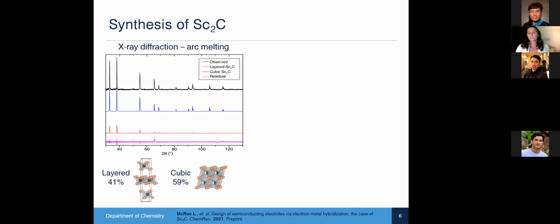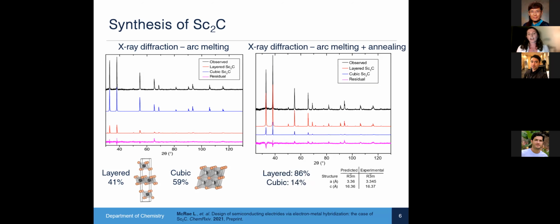So in order to overcome this kinetic barrier, we followed arc melting with a 7-day annealing at 1100 degrees Celsius. And the diffraction pattern that we get after annealing shows that we end up getting more of this thermodynamic phase. So we get mostly the layered phase after annealing, and the predicted structure and the experimental structure line up very well, which supports the idea that we were indeed able to make this layered discandium carbide phase.